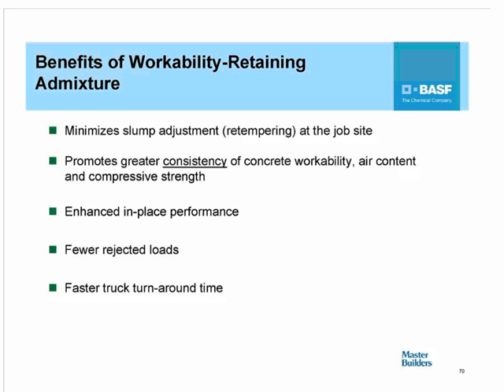concrete producer. So just to summarize, the benefits of the workability retaining admixture basically lie in the fact that it helps to minimize slump adjustments or retempering at the job site, and as a result of that, promotes greater consistency of concrete workability, air content, and compressive strength, which invariably enhances the in-place performance of the concrete mix and leads to fewer rejected loads as well as faster truck turnaround time.